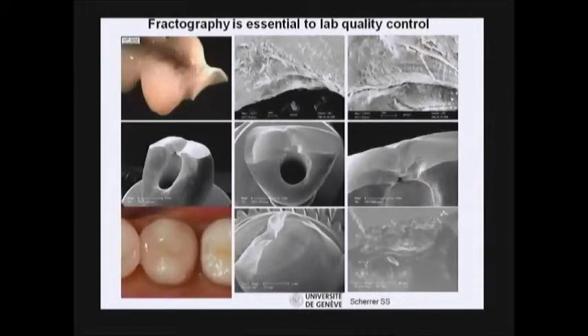Fractography is essential also for lab quality. You can verify if the laboratory has worked properly. For instance, this bridge failed after 9 months. It's a 4-unit bridge. And you can see that at the connector size, at the connector gingival side, we have sinter cracks. And the sintering was not capable of closing the cracks, which tells you that that crack happened in the green stage grinding, or in the oven at the beginning of the sintering with the piece that shrinks with a stress somewhere. Of course, you can see some grinding marks from the laboratory afterwards as well.